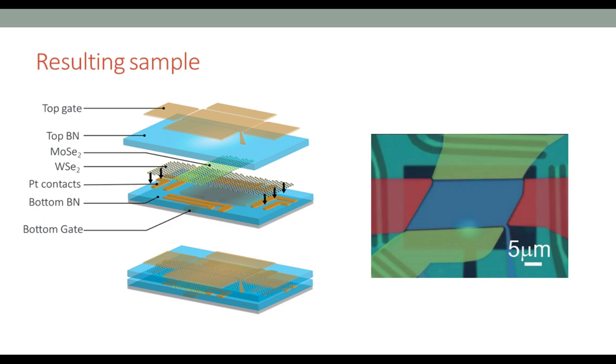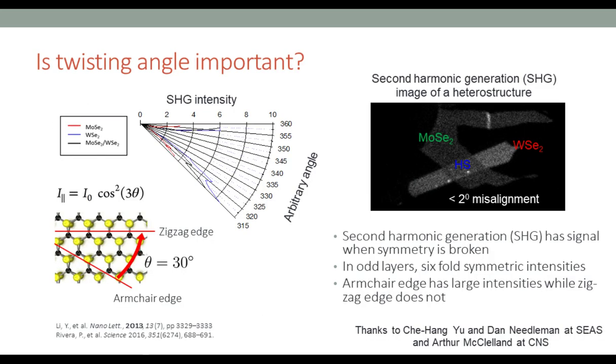I didn't mention this, but it is actually quite important to line up the momentum space, or the crystallographic edges, of our sample. And so we use a technique called second harmonic generation. This is a technique that allows us to align the edges of our materials. We rotate our sample and check our second harmonic generation intensity, and then we can use this to align our sample with 60-degree symmetry.